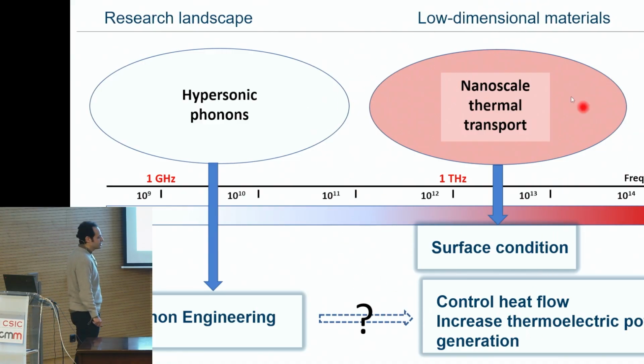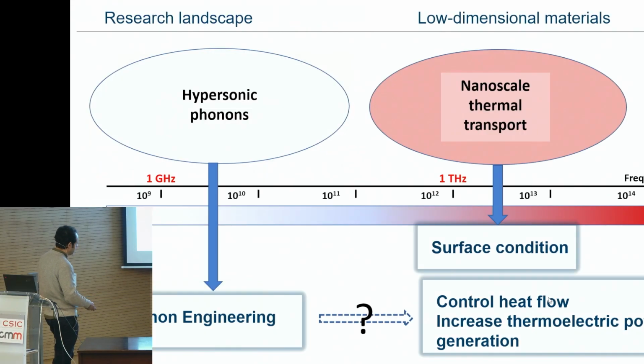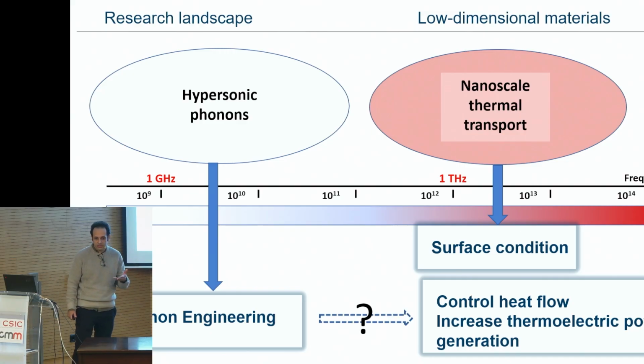So, if we think about the phonon spectrum, we are interested to see the high frequency phonons actually. We want to employ these phonon engineering approaches in order to see if we can control the heat flow, and potentially we can increase the thermoelectric power generation, and we want to have access to the high frequency phonons, the phonons that have high energy, and usually in low dimensional materials this happens for phonons above 1 terahertz. And this is the spectrum of phonons that we would like to control.